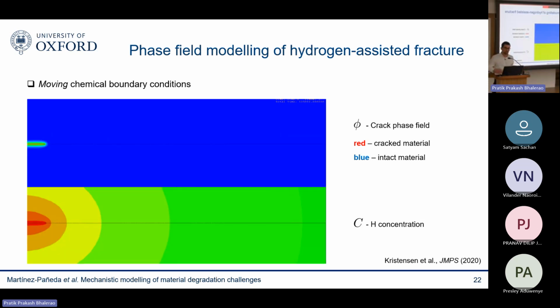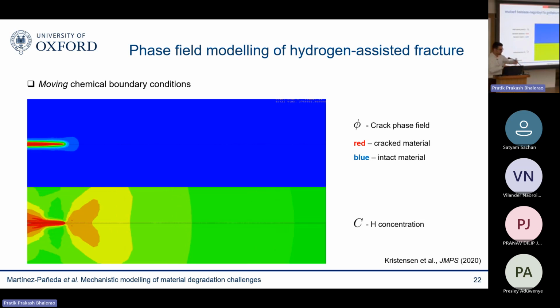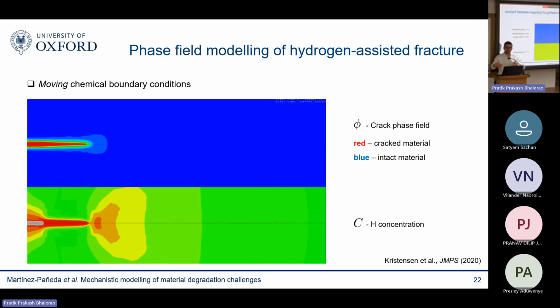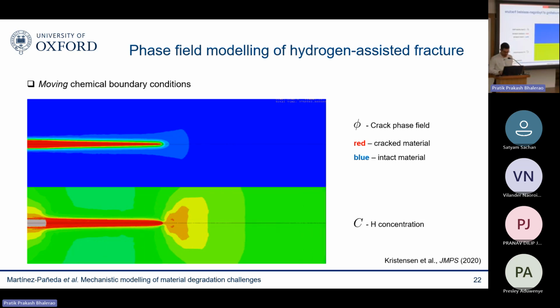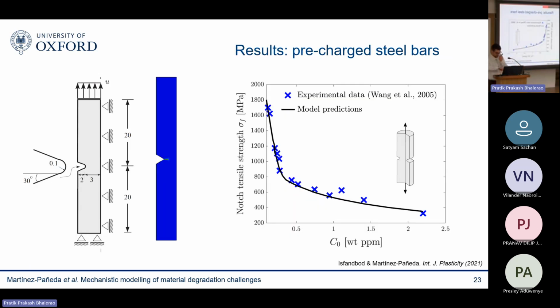And there are multiple ways you can do it computationally, either through a penalty approach, for example, or by enhancing your diffusivity in the regions where the phase field is larger than 0.9, for example. So this is the beauty of phase field. You always have full control on what your damaged regions and undamaged regions are without any special treatment. So let me show you some representative results.